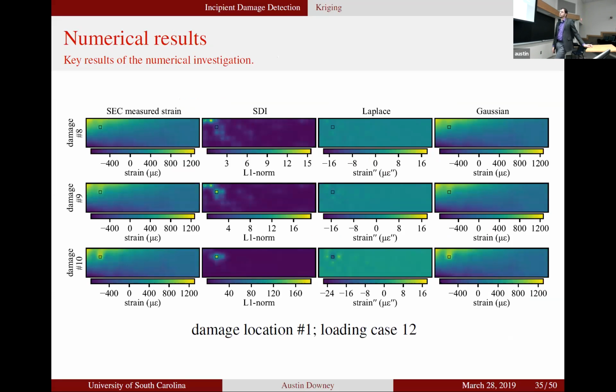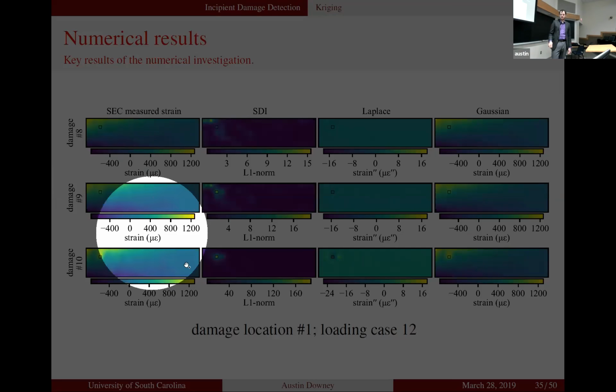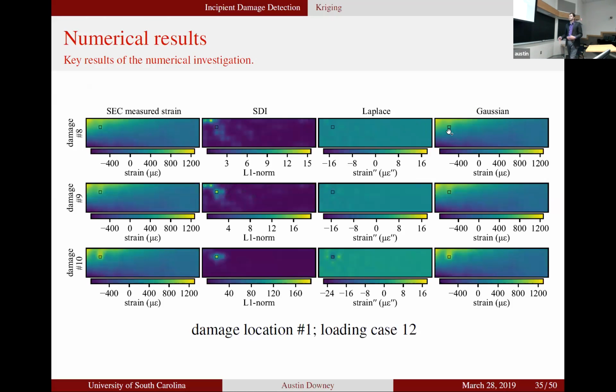We just increased damage by reducing the stiffness. And so what we end up with here is strain maps in the left column. So this is what's actually measured. And this little square here is the damage. The spatial damage index, which is the algorithm we just discussed, is in this column. And then Laplace and Gaussian gradients, which are commonly used damage detection algorithms for spatial image reconstruction.